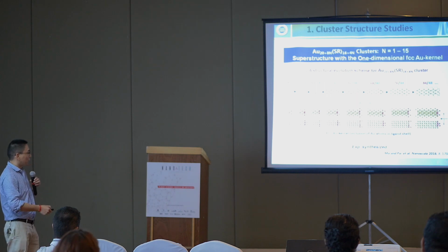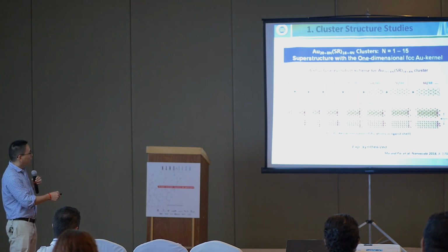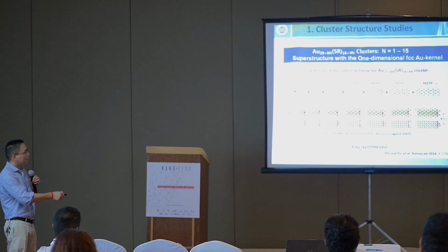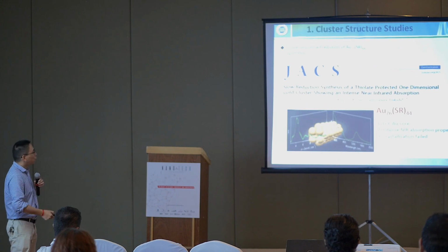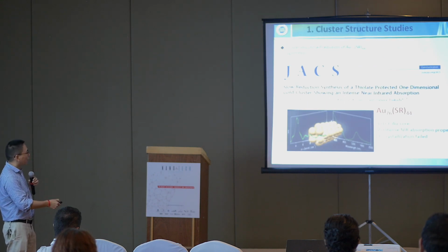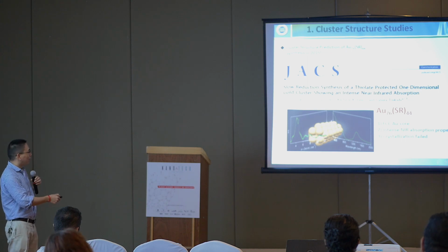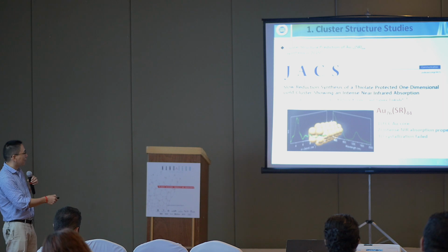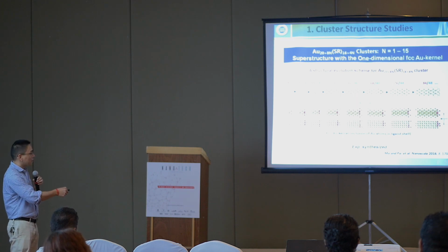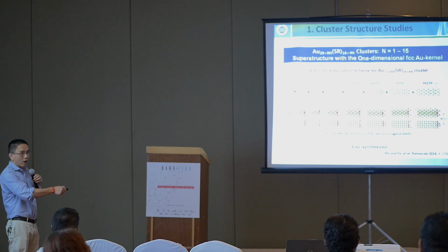Okay, with this knowledge, we further consider, since these four have been reported by experiments, what about these last ones? Here, here, here, and here. In 2015, a group from Japan reported the synthesis of a thiolate-protected gold cluster with a formula of Au76(SR)44. Oh, we find that this cluster fits very well with this homogeneous cluster series with n being 7.